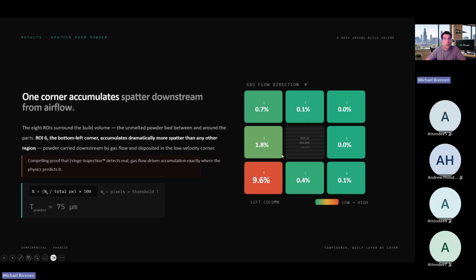In order to threshold each of these pixels, we basically set a threshold of a 75 micron deviation from the normal plane, and said if the pixel measured above 75 microns, that was a spatter pixel, and then we measured that as a percentage of the total number of pixels in this region of interest. And what you'll see is that we found a very large spike in this bottom left corner.